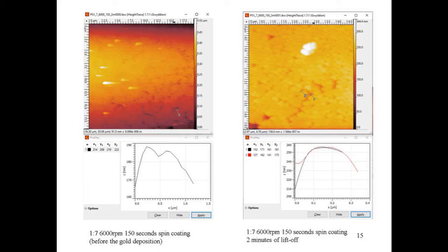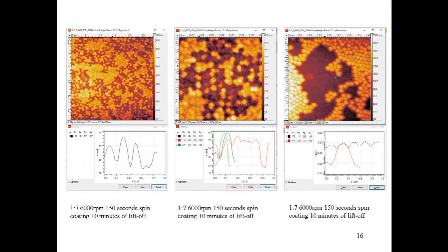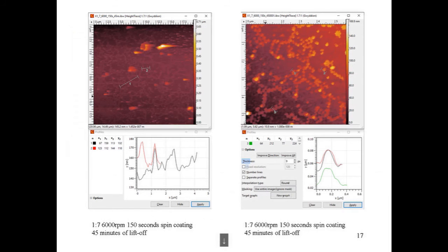Checking after 2 minutes of liftoff, we can understand the nanospheres were not fully removed, and we continued lifting off. After 10 more minutes of lifting off, there were still polystyrene nanospheres around and under the gold particles. Hence, the structure starts falling apart in pieces. Lifting off for 45 more minutes shows that we were not successful in removing the nanospheres under the gold particles.